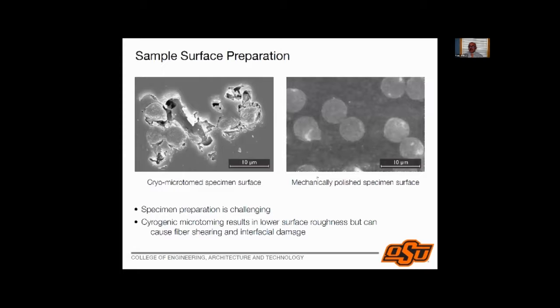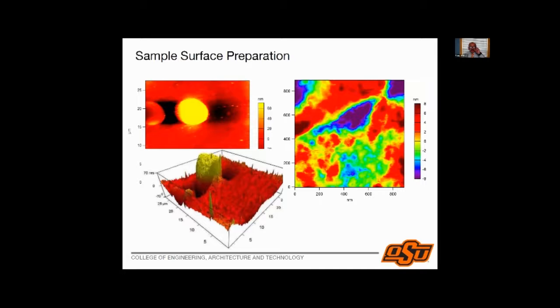Cryomicrotoming doesn't work, mechanical polishing works. And these are the carbon fibers you're looking at. So these are the 5-micron carbon fibers. This is the epoxy. And we carry out all of our experiments in a tiny region right next to where the fiber sits and the matrix sits. That's where all of our measurements are made. So this gives you an idea of what sample preparation looks like.